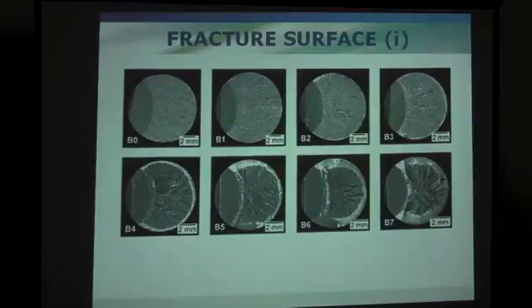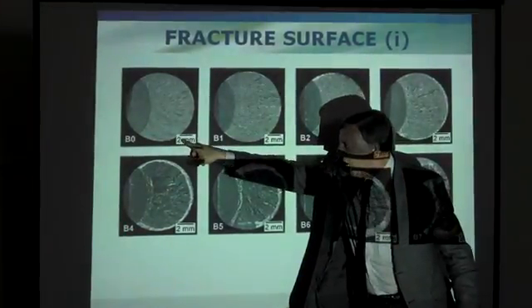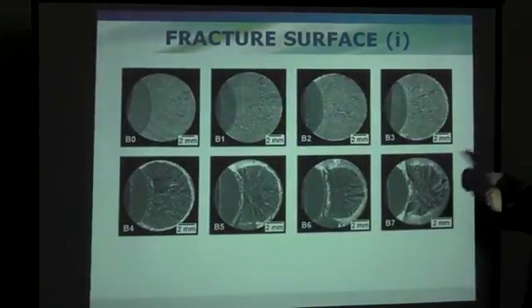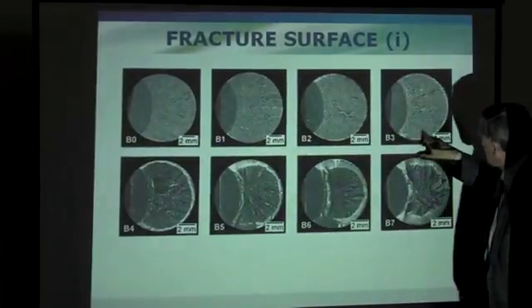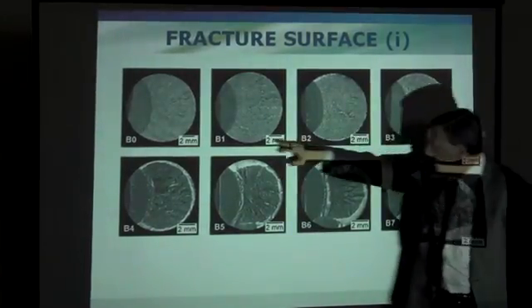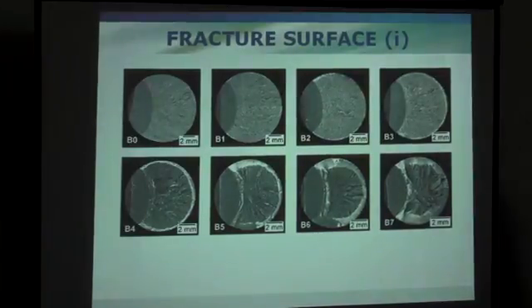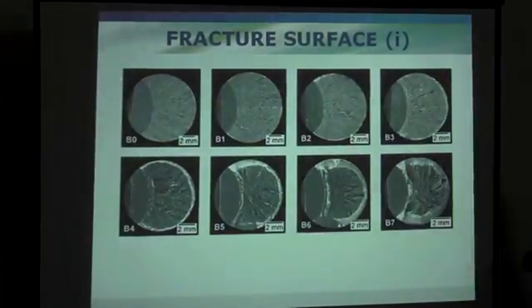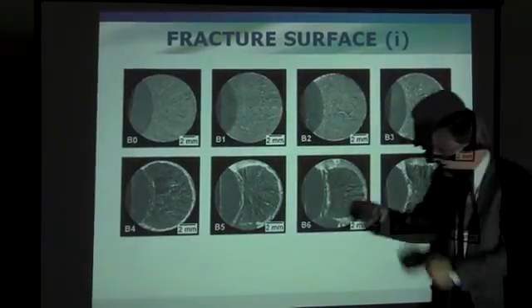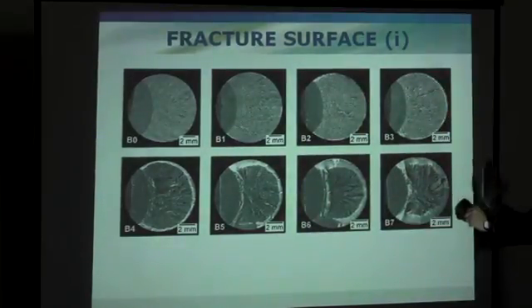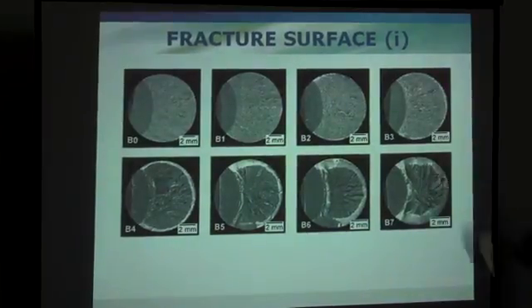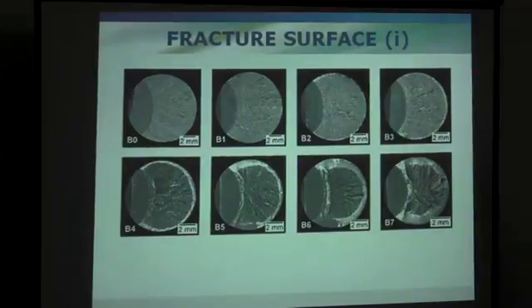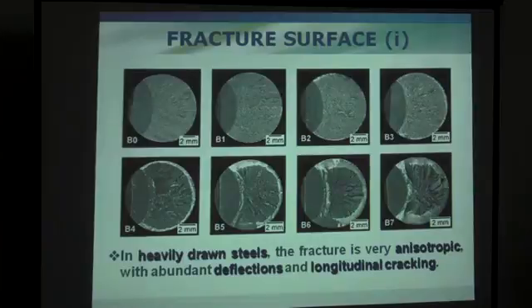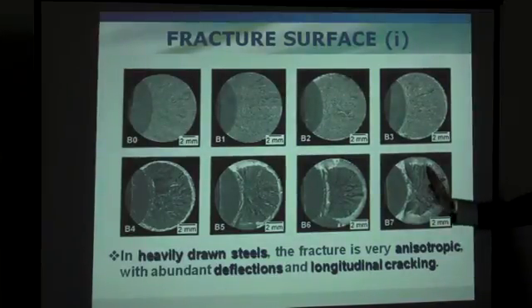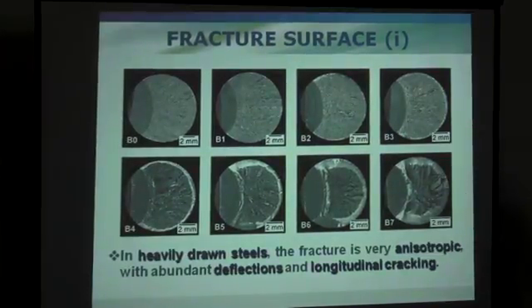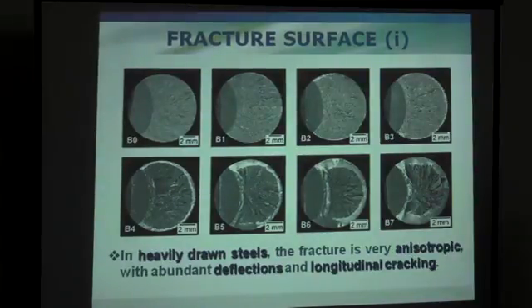Here is the appearance of the fracture surface with the evolution of progressively drawn steel: hot rolled material, not drawn at all, mode 1 fracture, purely isotropic; slightly anisotropic in the first stage of drawing, but roughly speaking it still breaks in mode 1. From 4 steps of cold drawing to 7 steps, we have a progressive anisotropic effect with crack embryos, crack branches, crack deflections, and a very stepped, very rough fracture appearance because of the microstructural orientation. In heavily drawn steels, the fracture is very anisotropic with abundant deflections and longitudinal cracking, longitudinal splitting or delamination between two similar microstructural levels, either the colonies or the lamella itself.